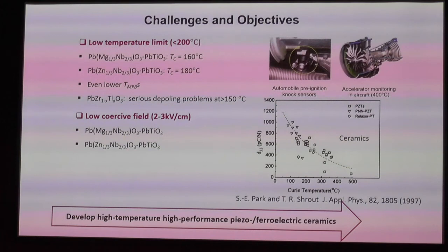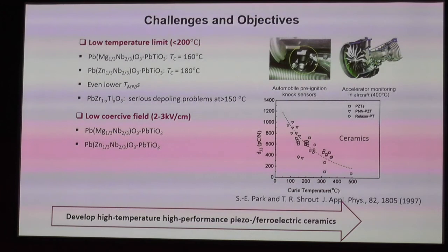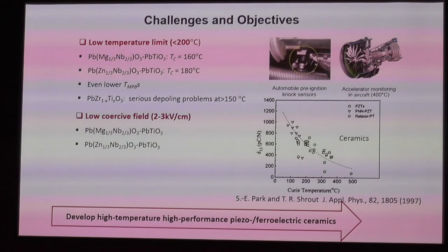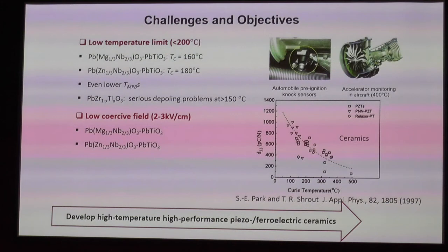depolarization temperature. And one more problem is that the coercive field is comparatively low, 2-3 kilovolt per centimeter typically, which makes the material not very stable, especially at elevated temperatures. But high temperature materials are needed. And here we show a review of existing materials, piezoelectric ceramics, which can work at high temperatures.